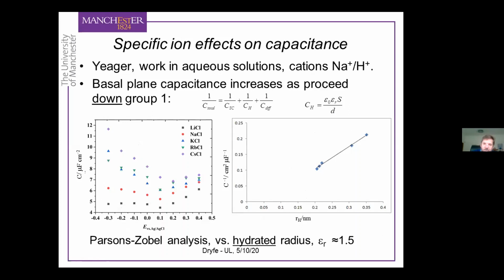And we in fact see, when we've looked at this, quite different capacitive responses for different simple alkali metal chloride solutions. You can see at the negative branch of the capacitive response, where the capacitance is dominated by the cation adsorption, that the capacitance response is really sensitive to the identity of the cation. As we go down group 1, as we go down the period, basically the capacitance increases. So that's quite an interesting effect, this kind of specific ion effect on the capacitance of this graphite electrolyte interface.